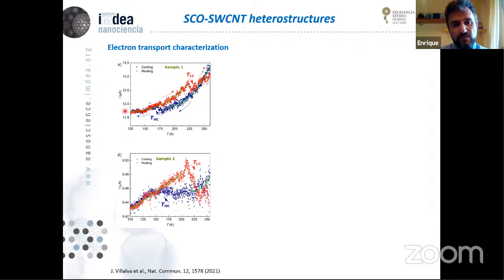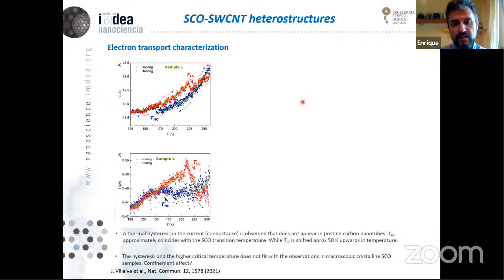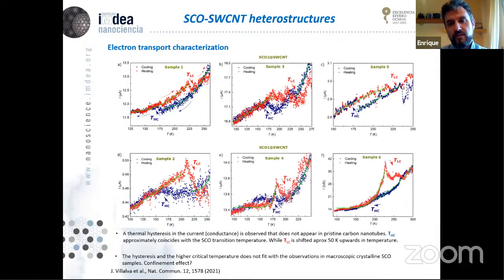If we now continue increasing the temperature, what we see is that there is a tiny jump here, but actually the current continues to be in this high conductance state until at around 225 Kelvin, it decays again to the low conductance state. And we see this in many of the samples. This, I think, is around 35%, which for us is quite big, actually.